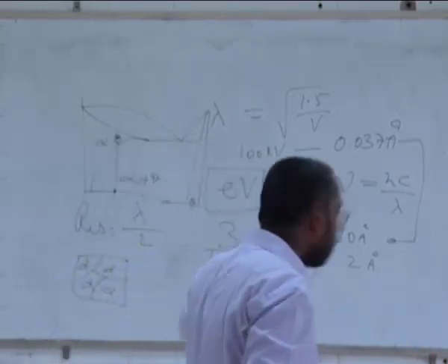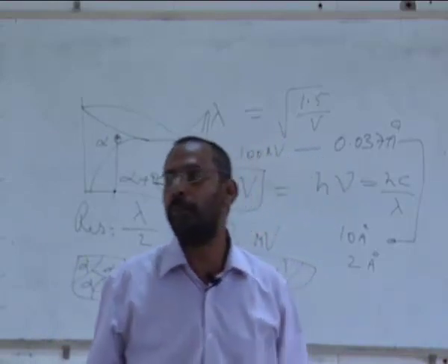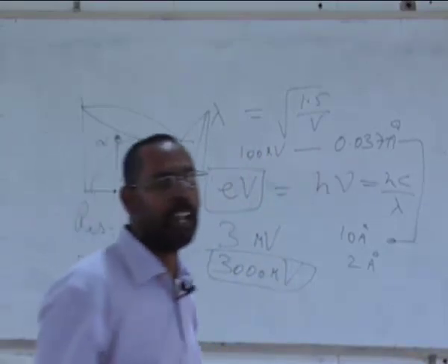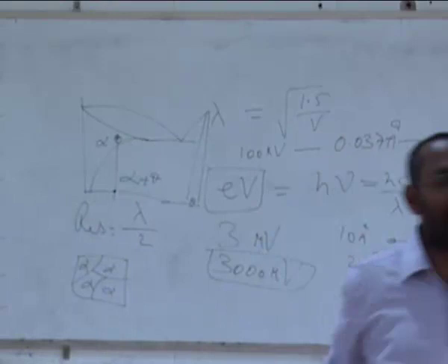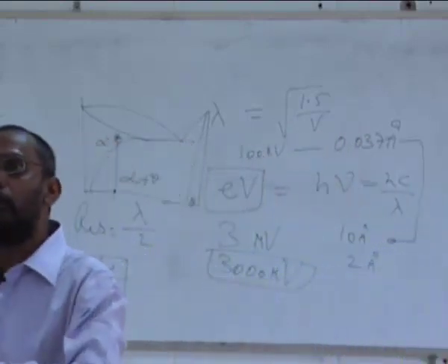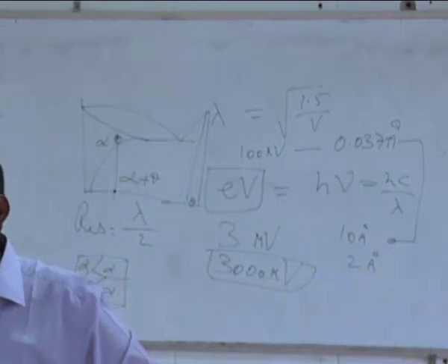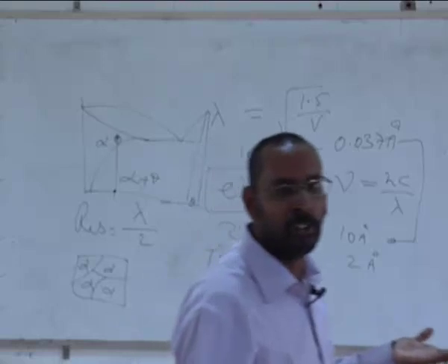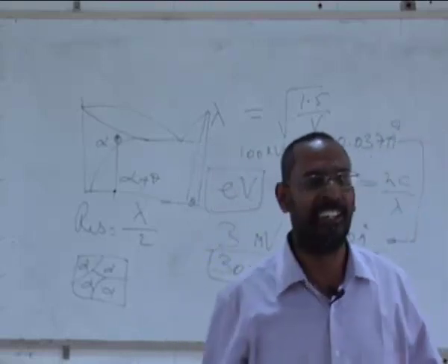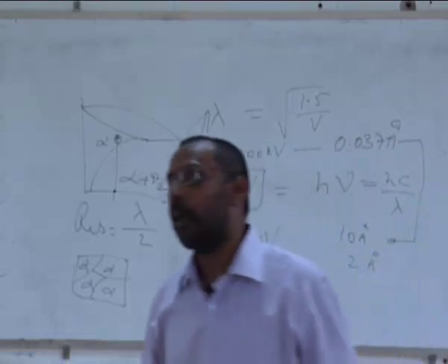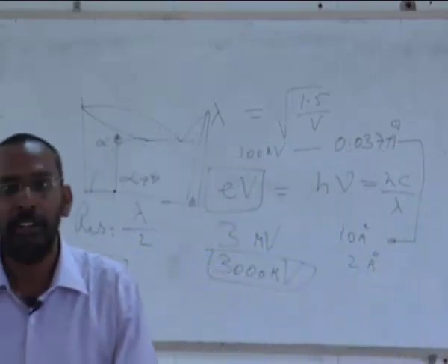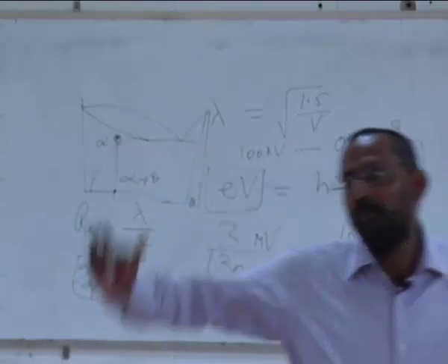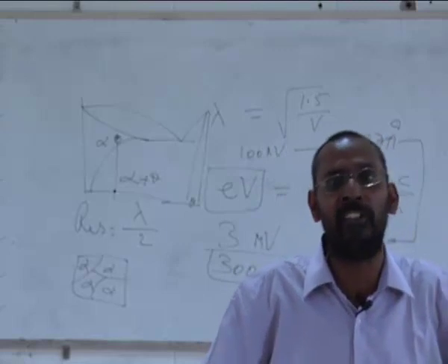But if I use such a microscope, after some time, actually, I will not see any more solid solution. I will start seeing the precipitates of theta inside the grains of alpha. Why? Because this particular beam has started heating up my sample, because the energy of the beam is so high that it has started heating my sample. And when I heat a supersaturated solid solution, what I do? I am actually aging it, right? So this is a problem. And if I take an aged sample, peak aged sample, I may see that after some time the precipitates might grow, because you must have heard of what is called overaging.